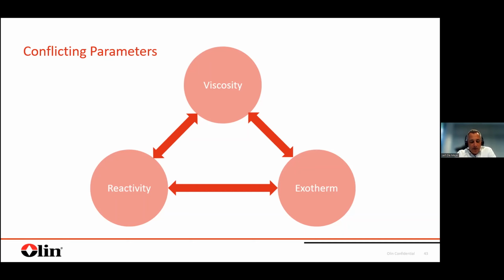And regarding reactivity, you want to have a low reactivity in the beginning in the bath, in the liquid phase, but as much reactivity as possible in the solid state to keep your post-curing cycle as short as possible. So this again is representing a limitation.